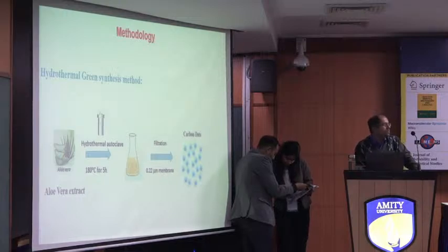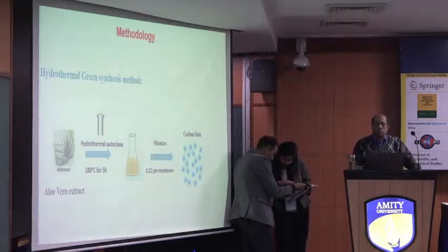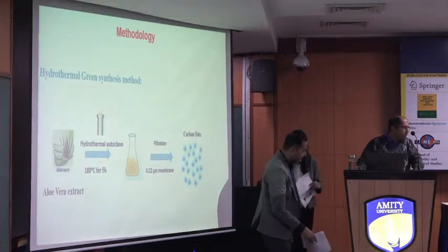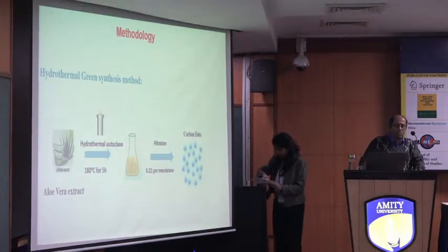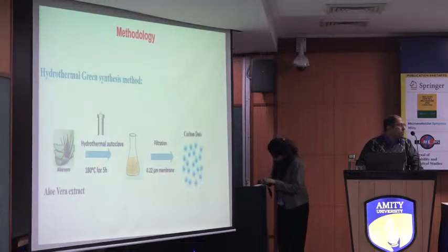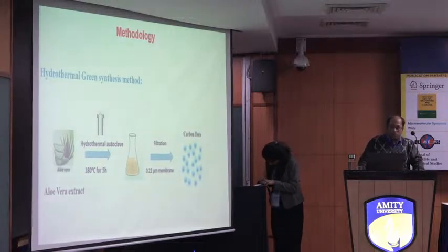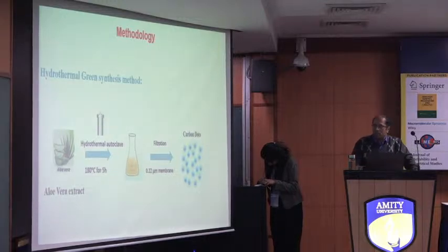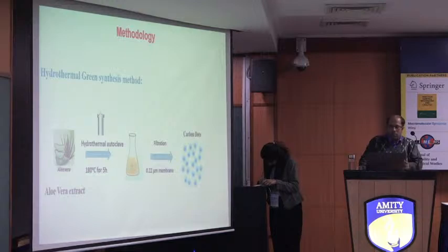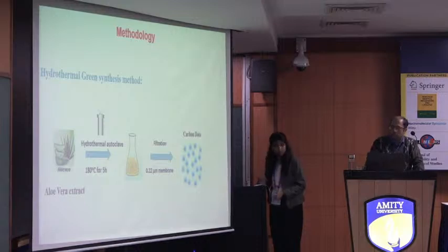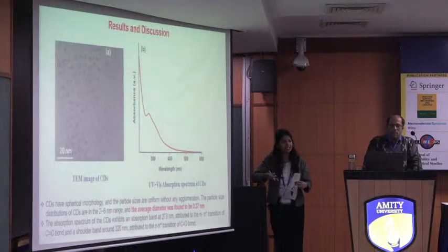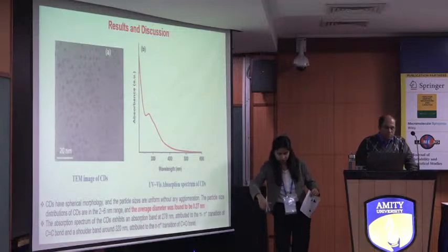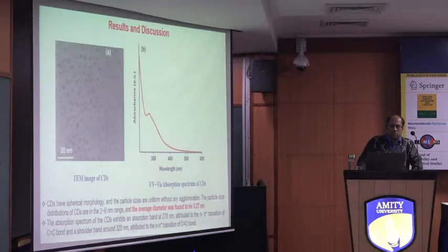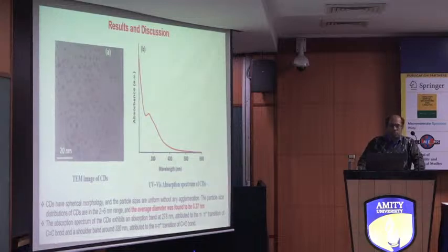Now, coming to my research work, I synthesized carbon nanodots using the hydrothermal green synthesis, which involves extracting the aloe vera gel and then putting it in a hydrothermal autoclave at 180 degrees Celsius for 5 hours, and then finally taking that impure carbon dots for filtration using a 0.22 micron membrane to obtain the pure quantum dots. These are the pure quantum dots obtained after the purification. To check the morphology and the size of the synthesized carbon nanodots, I performed the TEM measurements, which revealed an average size of 3.27 nanometers.